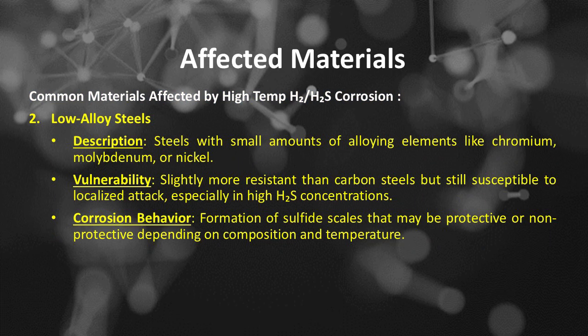The affected materials, number 2, is low-alloy steels. Steels with small amounts of alloying elements like chromium, molybdenum, or nickel. The vulnerability of the low-alloy steels: slightly more resistant than carbon steels but still susceptible to localized attack, especially in high H₂S concentrations. Corrosion mechanisms commonly affecting the low-alloy steels: formation of iron sulfides, prone to sulfidation and hydrogen embrittlement. The corrosion behavior of high-temperature hydrogen (H2) and hydrogen sulfide (H₂S) corrosion on these low-alloy steels is formation of sulfide scales that may be protective or non-protective depending on composition and temperature.